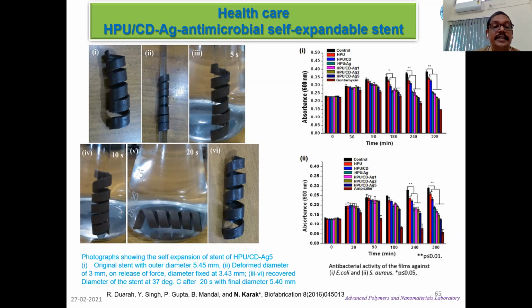So in our research, we have seen a self-expandable stent made up of bio-based hyperbranched polyurethane - this is starch-based - with carbon dot or silver nanomaterials. And when you get the expandability, original is 5.45 millimeter, and after expansion is 5.4 millimeter. So it's near about 98 to 99% self-expandability. Along with it, it is antimicrobial. This is also biocompatible.